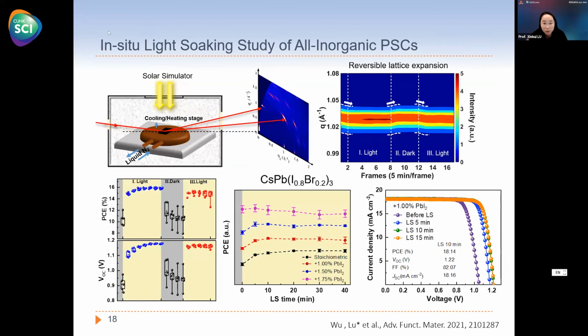And we also have some efforts to understand the operation condition of the perovskite solar cell, and we find that for inorganic perovskite solar cells there is a significant light soaking effect. So with our technique, we try to shine simulated sunlight and understand the lattice changing, and how the defect and passivation condition change with respect to this working condition, and to suppress or expedite this light soaking effect.